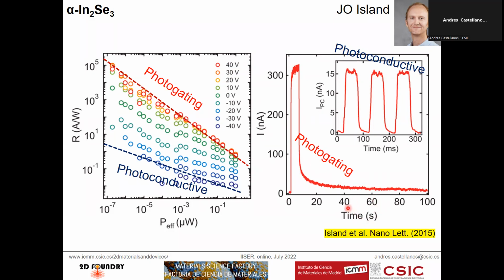If you go now to negative gate voltages and you repeat this experiment, then this speed is much faster. Okay, and now these numbers here are milliseconds. Because this is in the photoconductive effect, now you are not limited by this detrapping time. So you can indeed tune from a photogating photodetector that is very sensitive but slow to something that is rather insensitive in comparison, but much faster. And you can stop at any point in between. Okay, so by applying a gate voltage, you could easily decide which trade-off between responsivity and response speed you want to have.